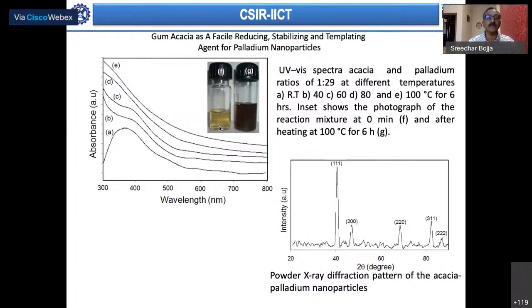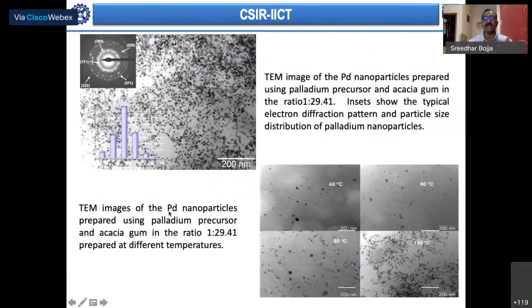This peak which you see here is due to palladium in its ionic form, palladium 2+. With time and heating temperature, by about 6 hours this peak completely disappears, which is an indication that this palladium 2+ has been reduced to palladium 0. We tried to do all the other characterizations like XRD and so on.